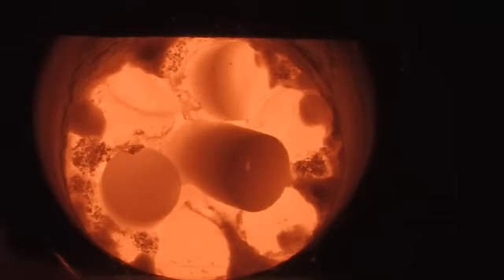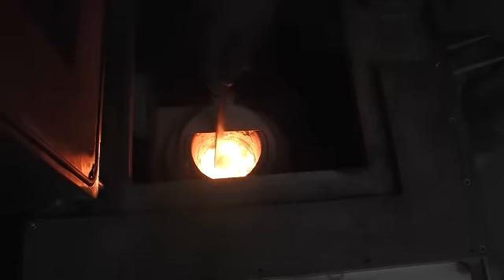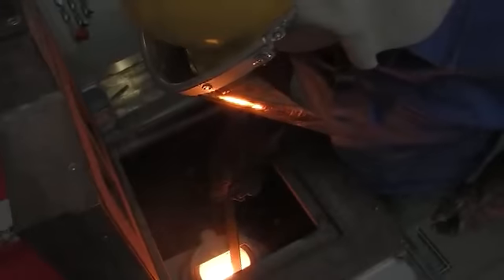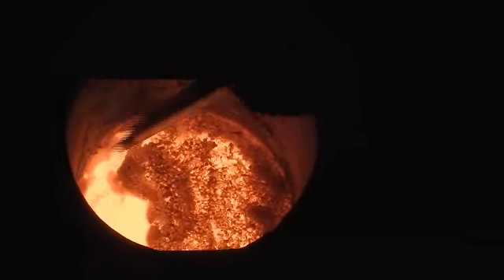After only a few minutes, the metal starts to change color and melts. Skilled casters can read the temperature of the metal from the color, red to white. Equipped with suitable protective clothing and the metal at a temperature of more than 1700 degrees Celsius, a binding agent is spread on top of the melt and the slag is manually skimmed.